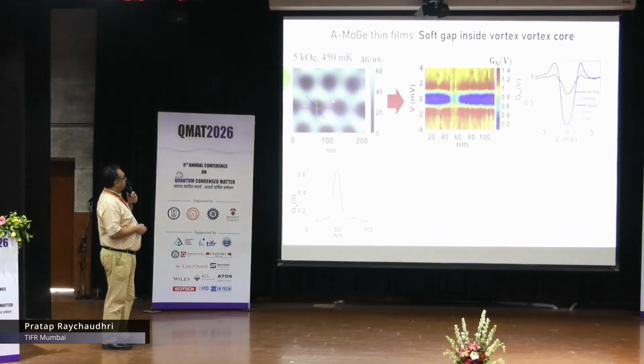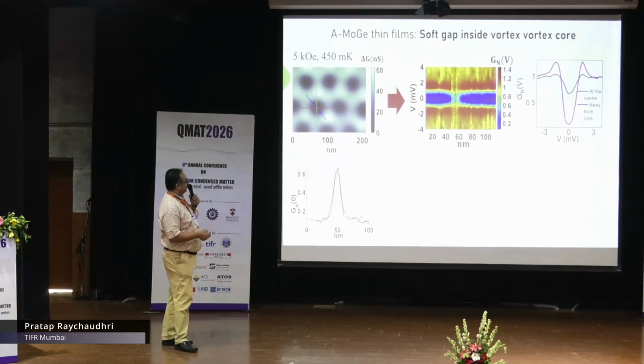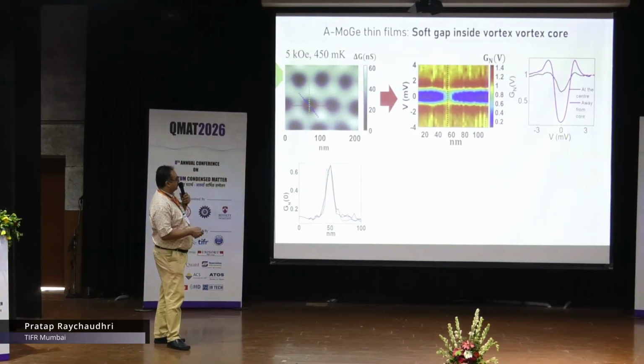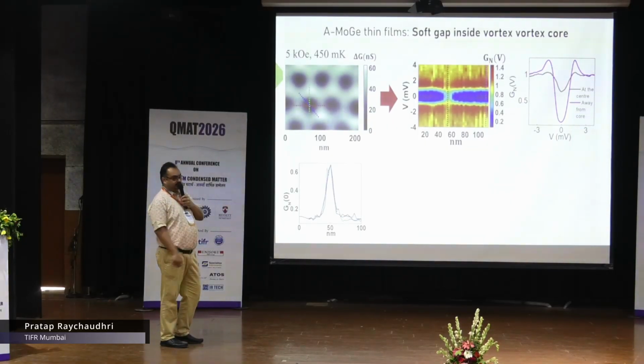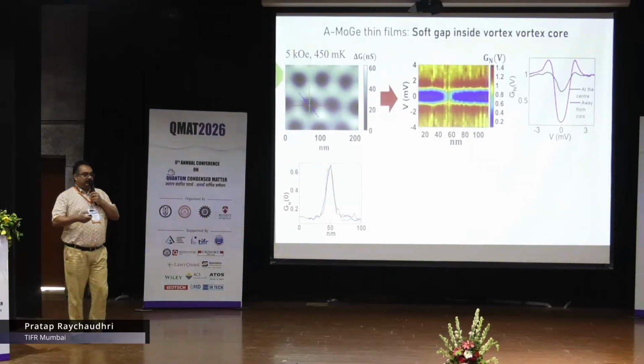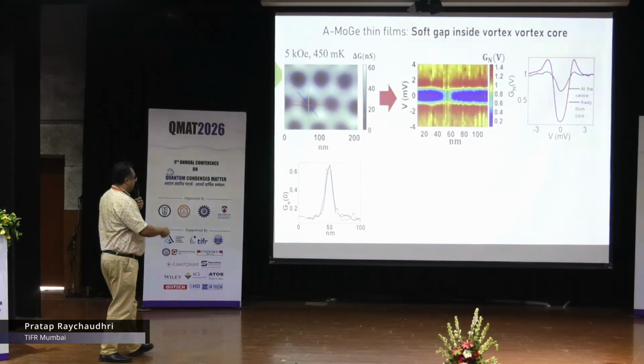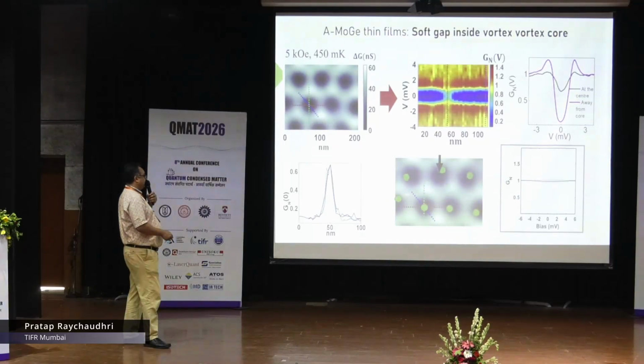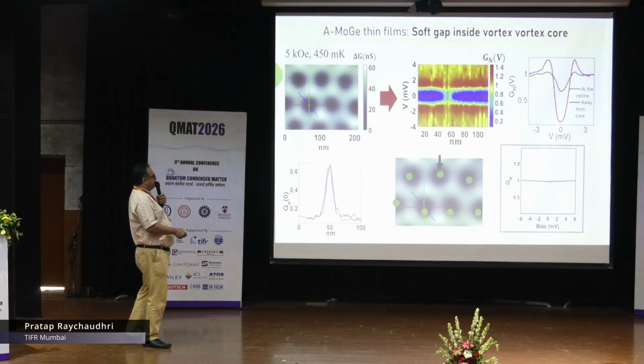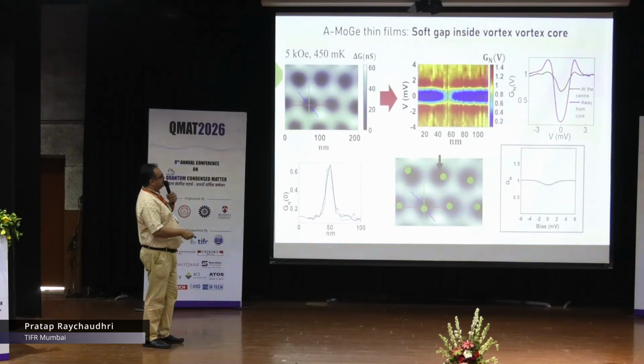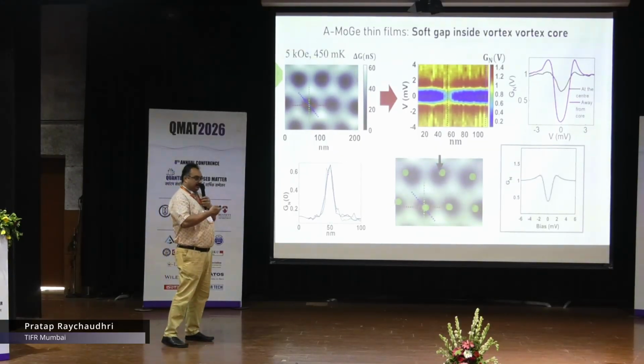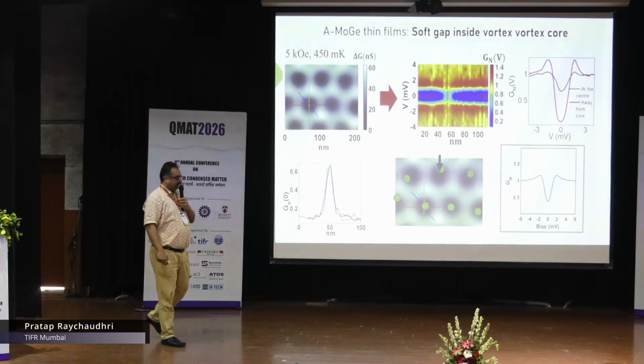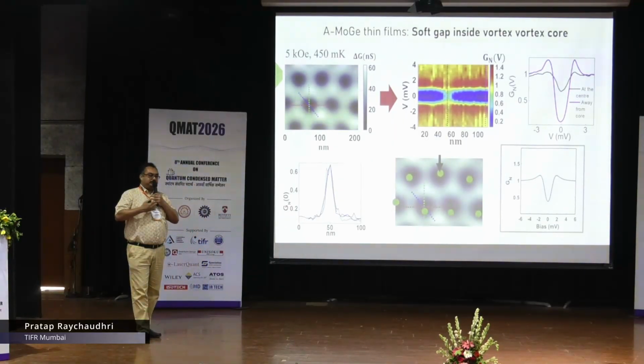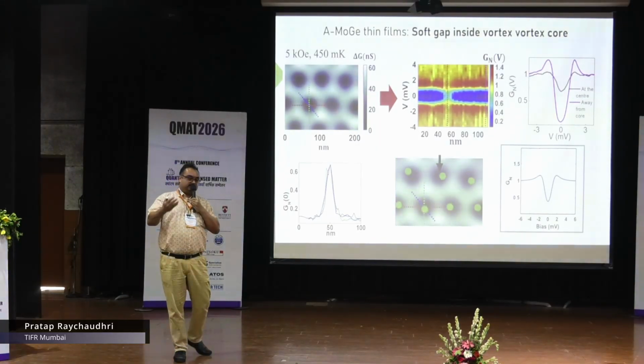What we had observed some years back, when we took a molybdenum germanium film and did this measurement, was something that we could not explain in any simple way. Outside the vortex core, of course, you have this gap and coherence peak, but exactly at the center of the core, you also have this soft gap and in fact even this small coherence peak. Now this is not accounted for in any theory where the vortex is static. So what we conjectured is that probably the vortices are jiggling around, as I have already alluded to once before. If I had a very fast measurement technique, I would see the spectra changing like this with time. But my measurement technique, STM, is slow, so it will average and I'll see something like this. The question is, is this motion caused by the quantum uncertainty principle? Is it a zero-point motion or is it just a thermal motion?